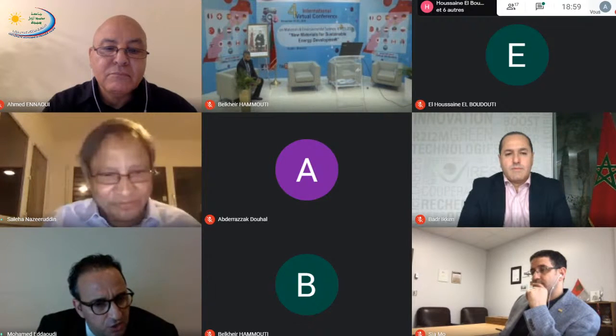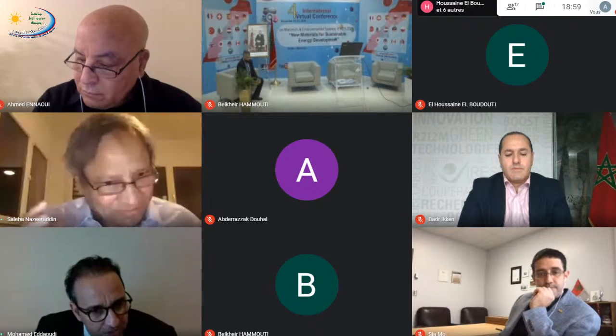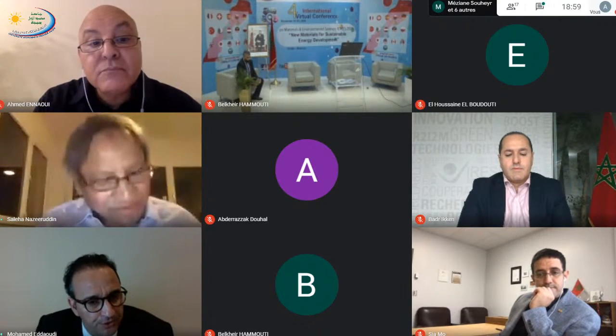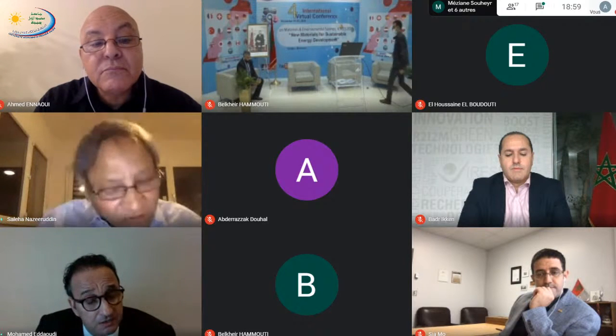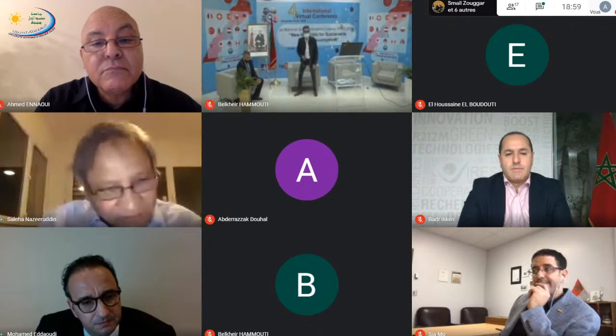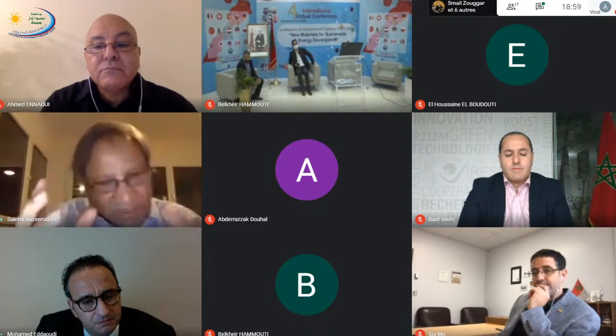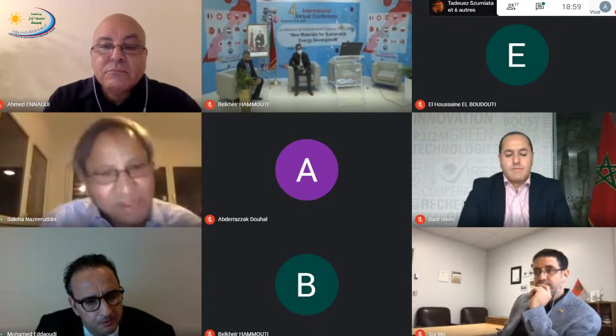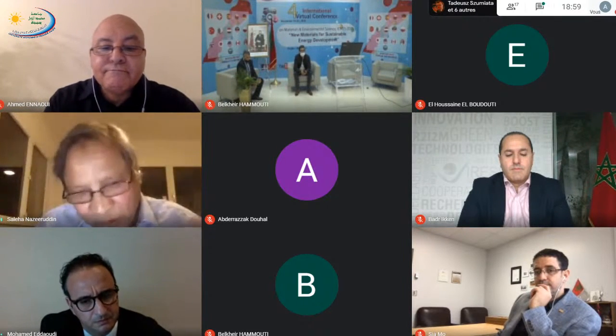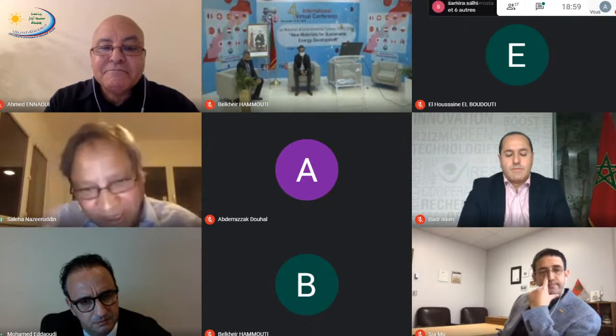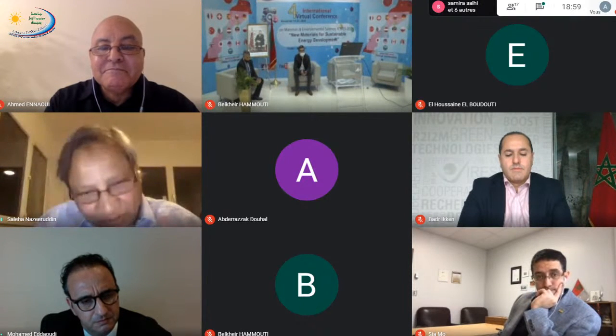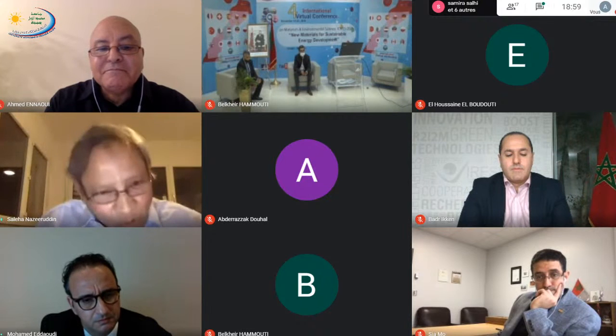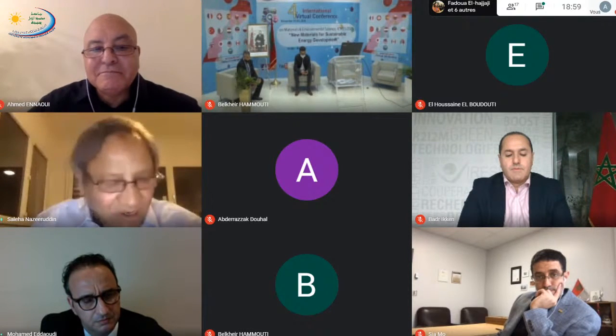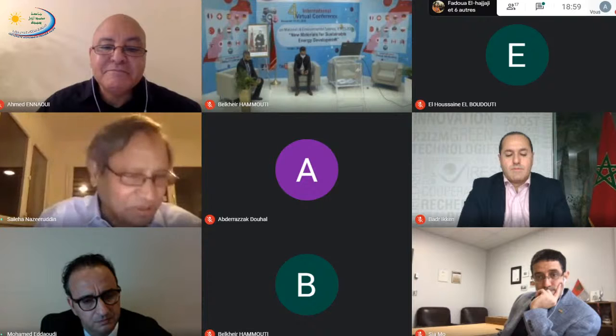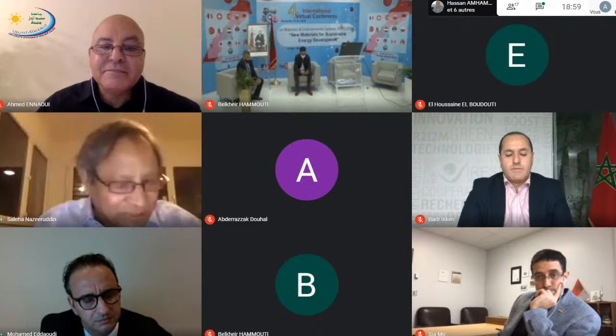So you are saying that you make your material a kind of hydrophobic surface, so it's not attacked by water? That's correct. This is a hydrophobic ionic liquid, which is forming a shell. And the second disadvantage of the perovskite is the ion migration because of the cation. Since we are doping with different ions, methyl ammonium, imidazolium, and halides, this compensates. So we are doing two things in one shot.